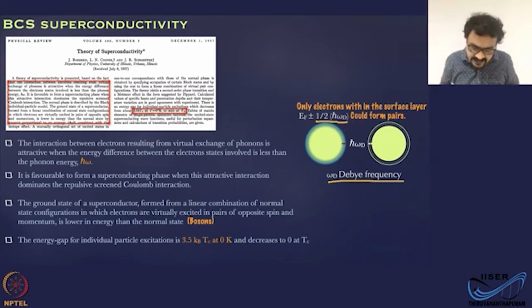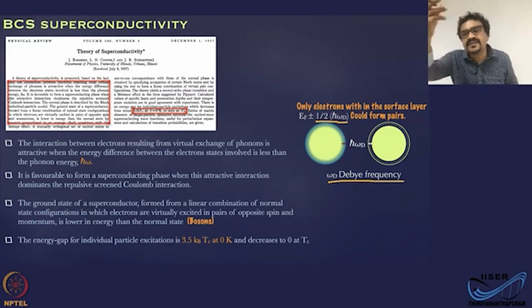So the energy gap for this single particle excitation, that is how much energy you need to supply to break this pair, these are the Cooper pair, is given by 3.5 kB Tc at 0 Kelvin. And this will decrease to 0 at Tc, because Tc is where you are going to get this Cooper pair. When you increase the temperature, this energy gap will reduce, and eventually the gap will close at Tc, the critical temperature.